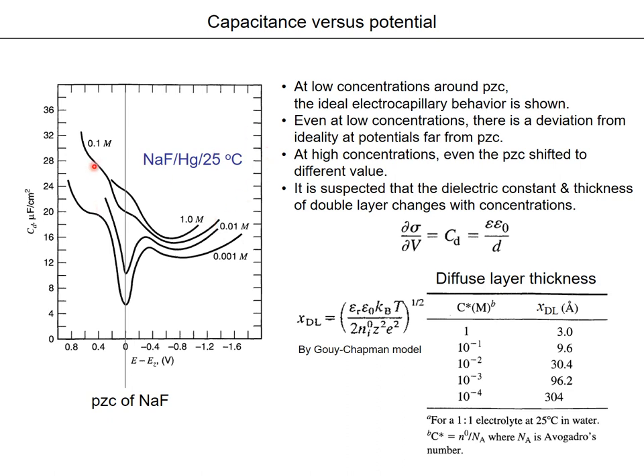At high concentration, like 1.0 molar, even the point of zero charge shifted from here to there, so two different values. This non-ideal behavior is suspected to come from the dielectric constant and thickness of the double layer changing with concentration. Capacitance can be described by the dielectric constant per the thickness of the double layer.